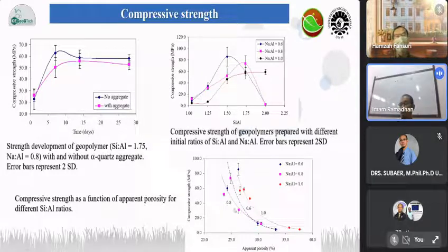So as I said before, you cannot avoid the formation of pores inside your geopolymer, but you can control it actually. You see the influence: the higher the percentage of porosity, the lower the compressive strength that you can gain.